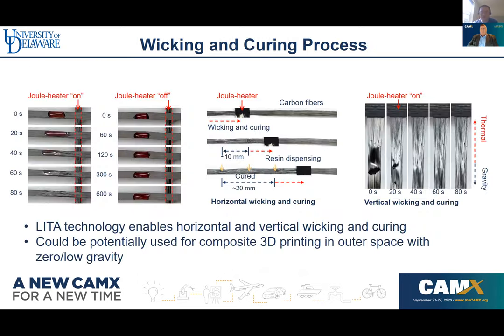And next, here is a very simple demonstration. We apply the Joule heater as our controlled temperature heater. If the heater is on, you can see the epoxy resin wetting and wicking into our carbon fiber tow, and it can flow toward the high temperature. But if the Joule heater is off, the epoxy resin can only stay on the surface of the carbon fibers, which means no wicking, no wetting, and of course no curing.